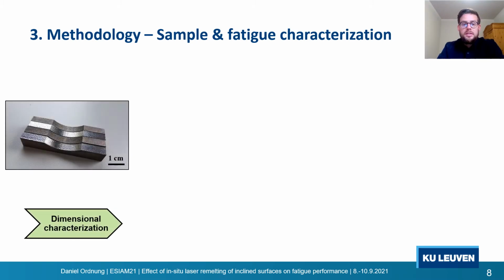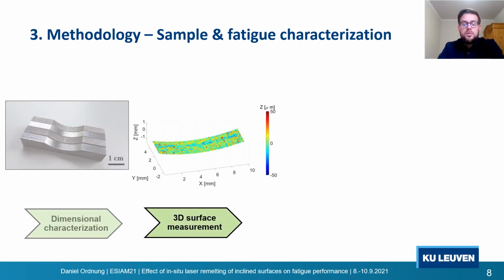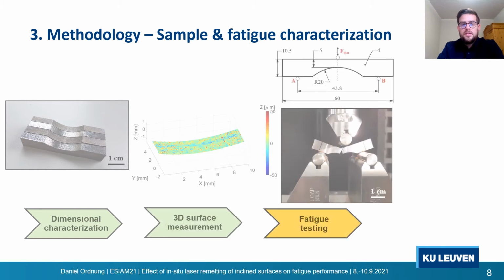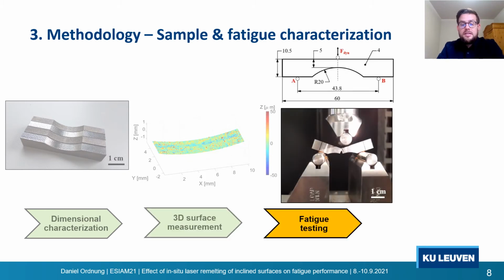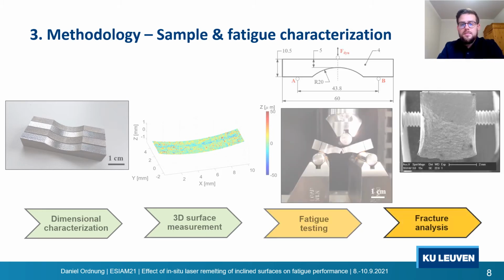For the sample characterization, two factors were mainly important. On the one hand, to measure the critical cross-section, and on the other hand, get a 3D surface measurement of the curved area to determine the areal surface roughness. The fatigue tests were done by 3-point bending test until failure or until 2 million cycles. If the sample did not fail after 2 million cycles, it was tested at the next higher stress level. The fractured samples were then assessed by SEM imaging.